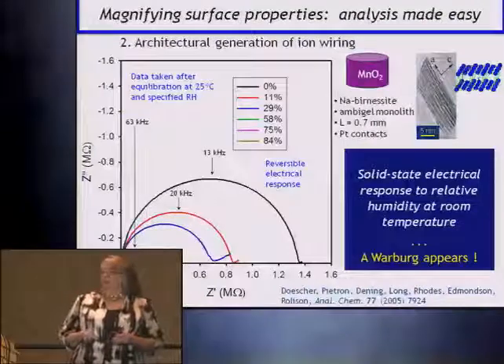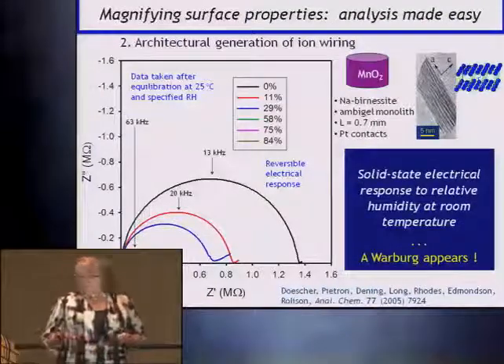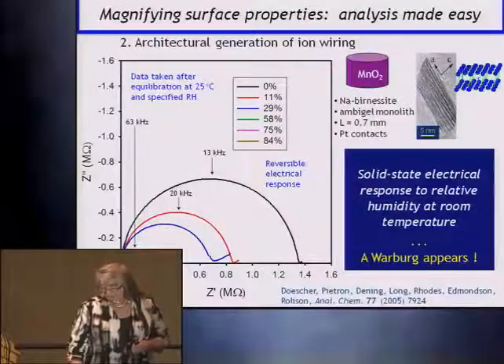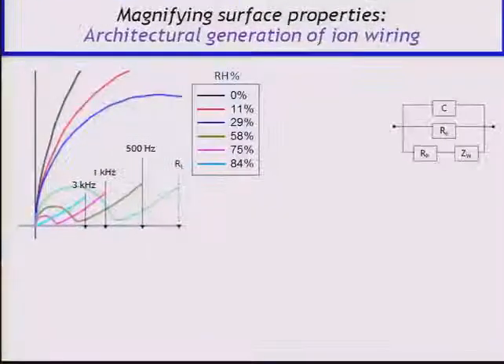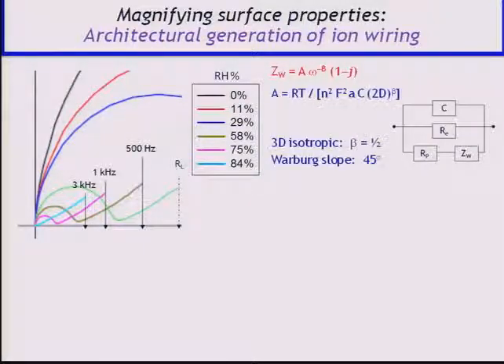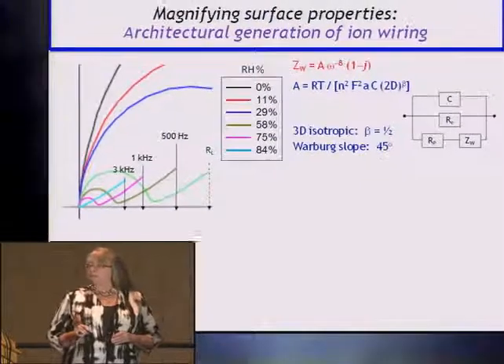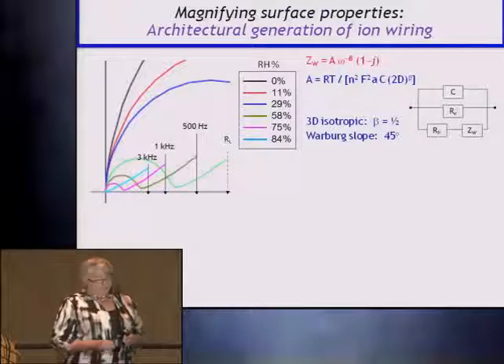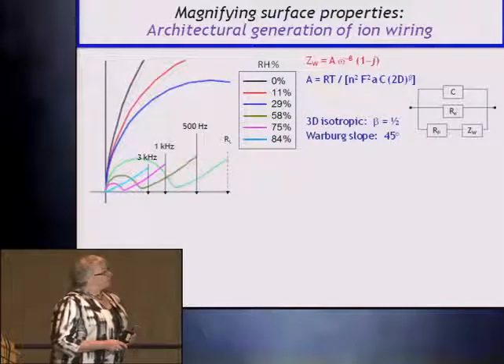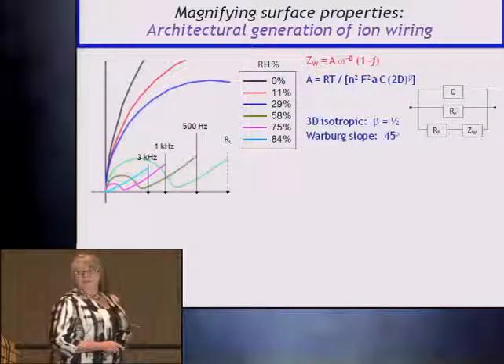Now, you usually expect to see a Warburg in a 3D isotropic medium, for instance, a liquid electrolyte. If you blow those data up, so we can't show the drier data here because they're closing over here, you can see the Warburg. You can do that analysis with that circuit. The most general form of the Warburg equation is frequency to the minus beta. And in 3D, like a liquid electrolyte, that's 1/2. That gives us the Warburg slope of 45 degrees we know and love. But there's also the Warburg coefficient, which has all the parameters we also know and love.